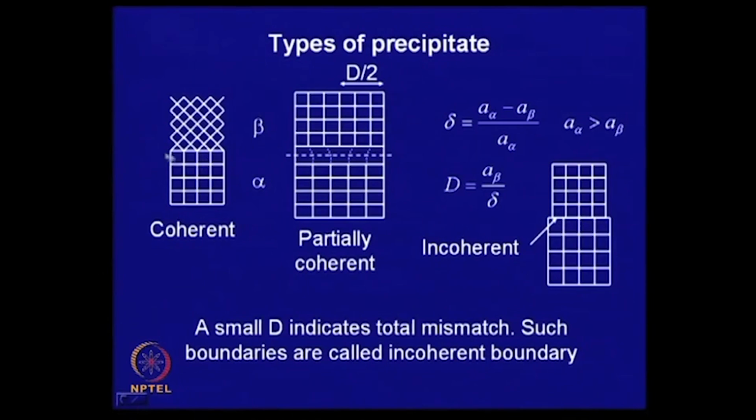the gamma which prevents. Here, since gamma is less, there is no surface energy barrier for the precipitate to form, whereas in this case you have the maximum surface energy barrier which must be overcome for precipitation to take place. So, this type of incoherent precipitate will definitely form on grain boundaries, grain corners or grain edges, and this will have intermediate characteristic.